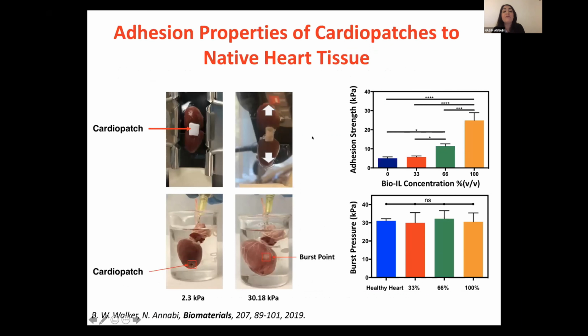On the top, you see wound closure test. My students formed a patch, they stick it to the heart, and as we add bioionic liquid to our formulation, it can form electrostatic interaction with the tissue. And we also add light, it also chemically bonds to the tissue, so we can achieve adhesion. And we show that by adding more bioionic liquid, we can have better adhesion on the heart.